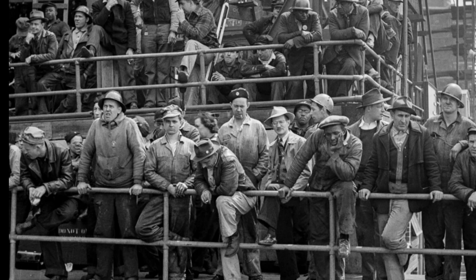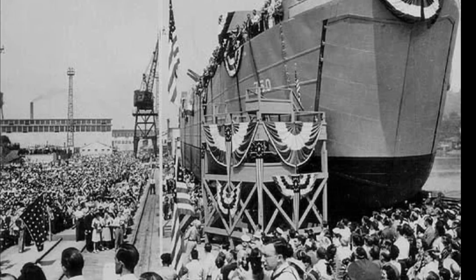Traditional riveted ship construction had developed over centuries of trial and error. Overlapping plates joined by mechanical fasteners created natural discontinuities in the hull structure. Each riveted seam was a potential weak point, but also a crack arrestor. If a crack initiated in one plate, it would travel to the riveted joint and stop, unable to propagate into the adjacent plate because the connection was mechanical, not metallurgical. Ships built this way could sustain local damage without catastrophic propagation.